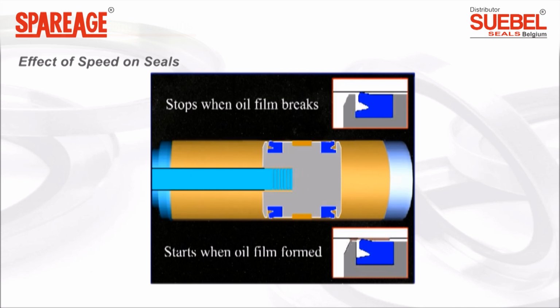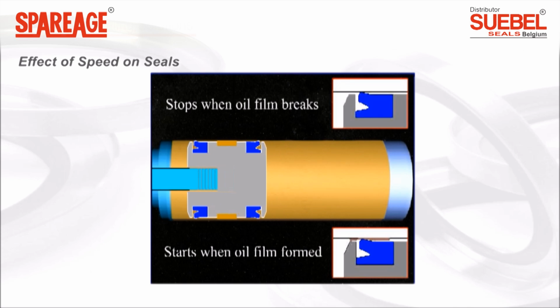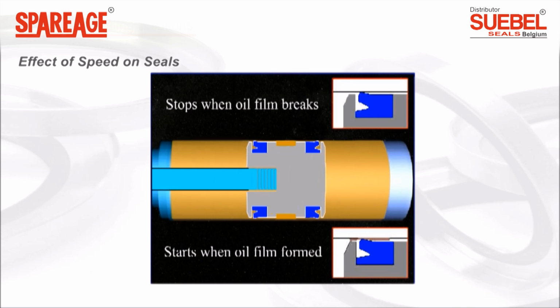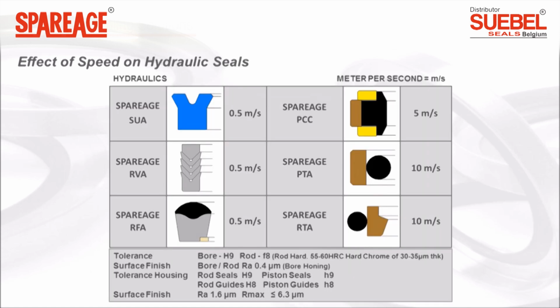Teflon material is self-lubricating with fillers such as bronze, making it ideal for applications where the media does not offer lubricating properties. Please refer to the Spareage catalogs for maximum surface speed of various seals. Due to stick-slip movement, all elastomer seals like nitrile, Viton, and thermoplastics like PU have a limit of 0.5 meter per second, compared to 10 meter per second for seals like Spareage PTA and RTA, where the main sealing element is self-lubricating bronze-filled Teflon.